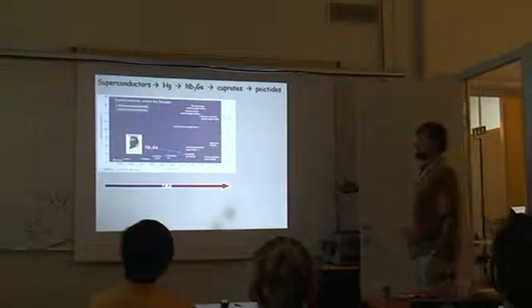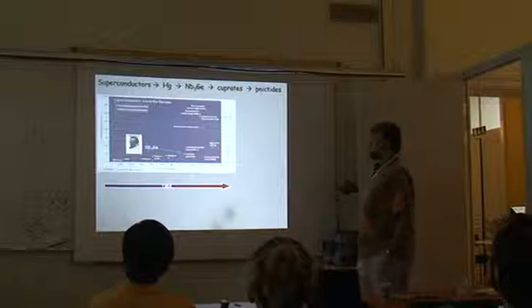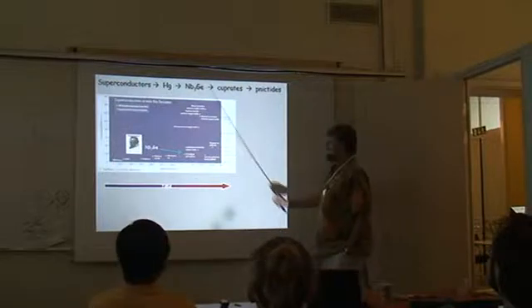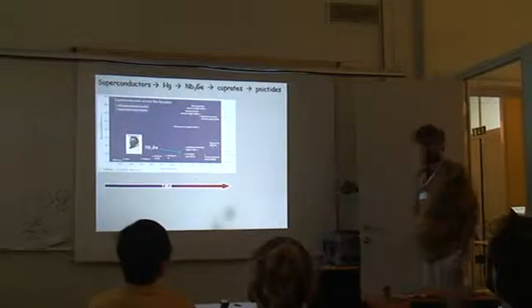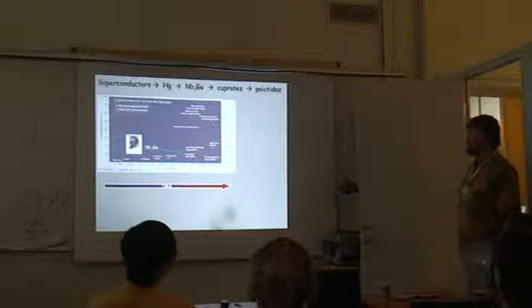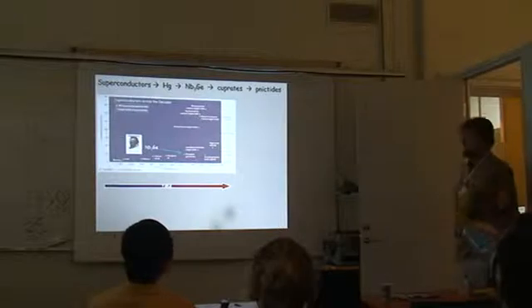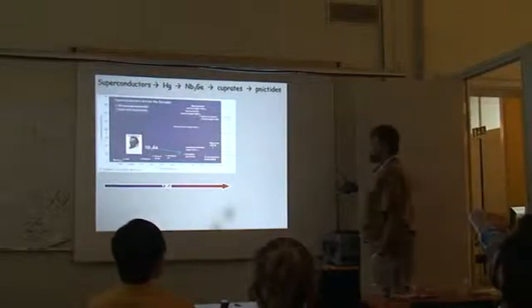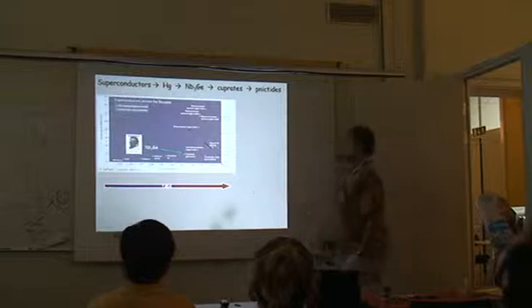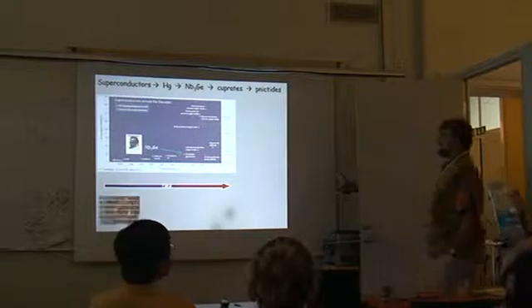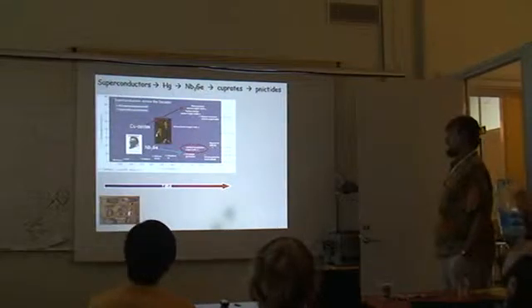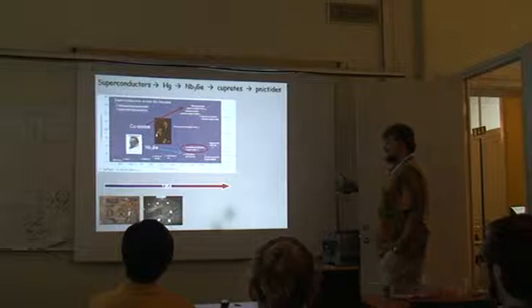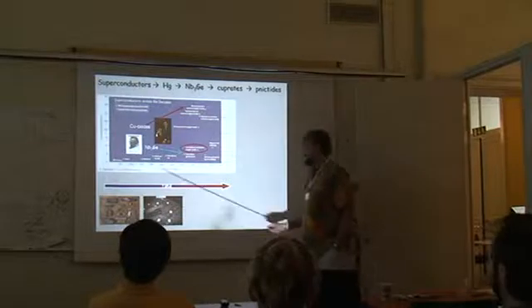So up to basically 86, the story was a story of many people trying to push the transition temperature laboriously a little bit up. Among the most successful was Bernd Matthias, and it is his material, niobium-3 germanium, that is a record-holding material with 23 and a smidgen Kelvin. Many of these materials today are used to make superconducting devices, particularly magnets. And we can fairly describe this as a rather stone age of superconductivity.